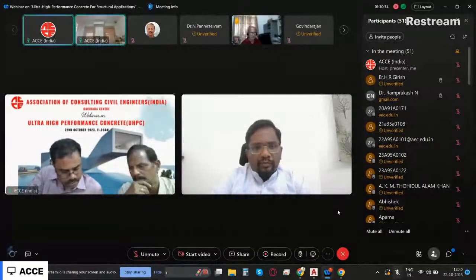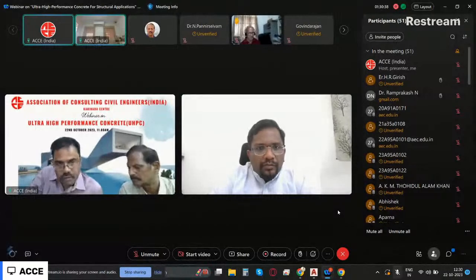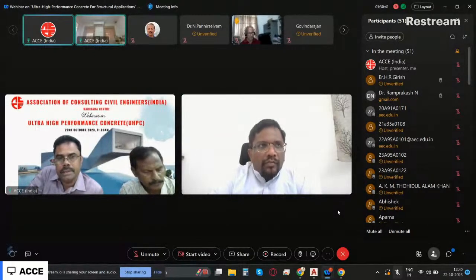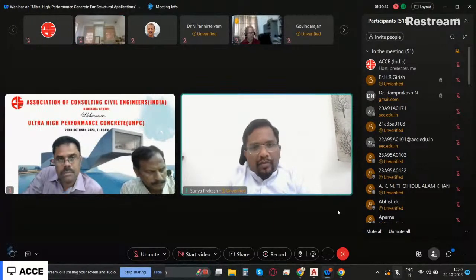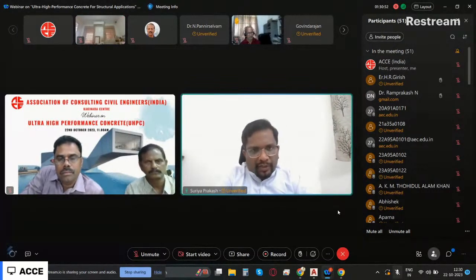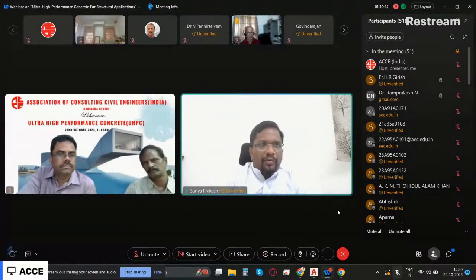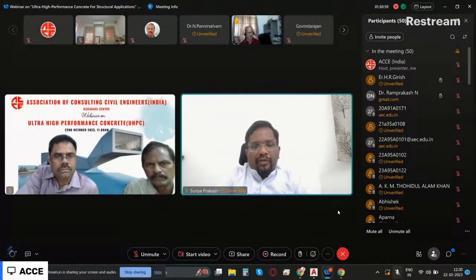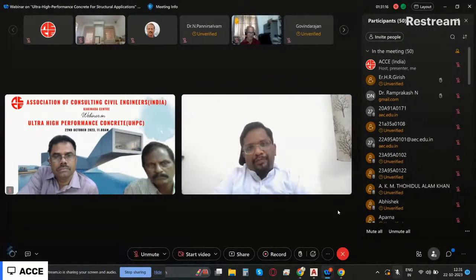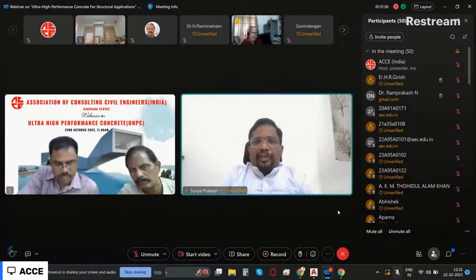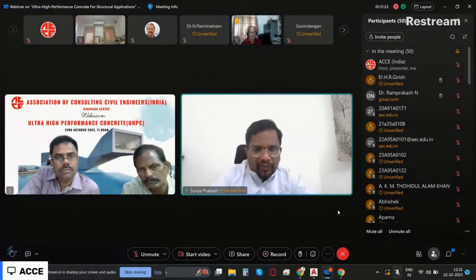Okay, sir. You mentioned that it's a low binder ratio and long mixing time. What will be the minimum mixing time, sir? Are there any guidelines? Those are the things that we are now generating data for from different guidelines. But here, what we use is a regular simple pan mixer. When we did that, we needed to mix for about 25 to 30 minutes for a volume of about 1 cubic meter. If you are using a twin shaft high speed mixer, then you can reduce the mixing time by about half, to 10 to 15 minutes. So that is ideal. That's what our trials are telling.